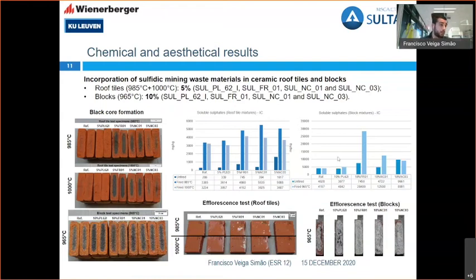On the blocks, on the other hand, as you see here on the black core formation, even the reference, because it's also a different material, a different product, an inner wall application, doesn't have the climate factor of the roof tiles. So the black core is also present on the reference. And then you see slightly all over a more denoted black core formation in all the other materials, even the Plombières material. So different mixtures definitely play a role here, and each product behaves differently, also the firing and sintering processes.